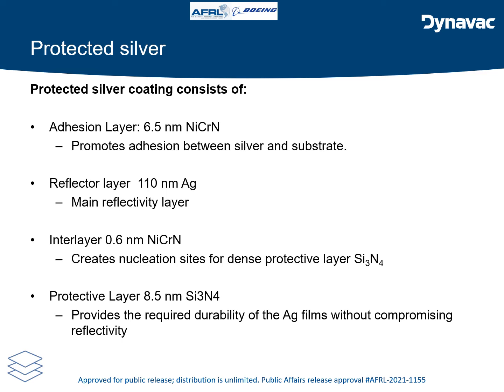Protected silver. Protected silver stack consists of 4 layers. First, adhesion layer. As we discussed before, silver has a poor adhesion to the substrate. Hence, an adhesion layer, which is a nickel chrome nitride, is added between the silver and the substrate. Then comes the reflector layer, which is the silver, followed by an interlayer, which is again a thin layer of nickel chrome nitride. This creates nucleation sites for producing a very dense protective layer. And finally, the protective layer, which is a silicon nitride. This helps with the durability of the films.